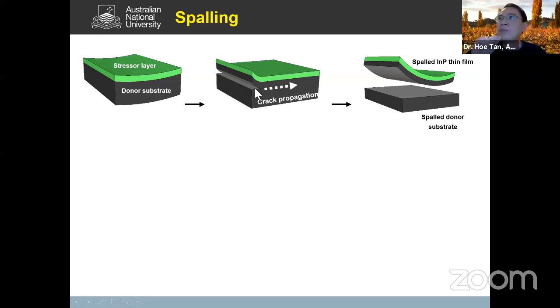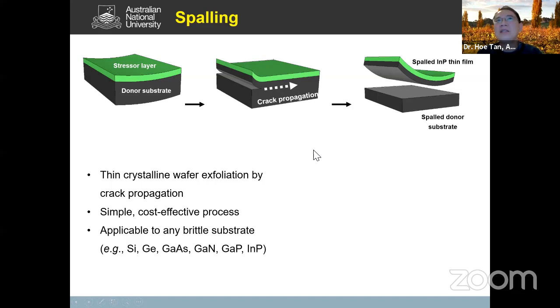So you can peel off gently along the crack, okay? And because this substrate is usually crystalline material, the crack can propagate along certain crystallographic orientation. Okay? And once you've done that, you can lift off the whole layer that you want. So this is a very interesting technique that you can exfoliate layers from the wafer.